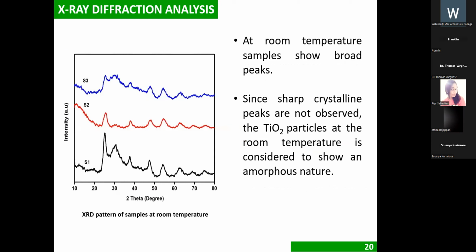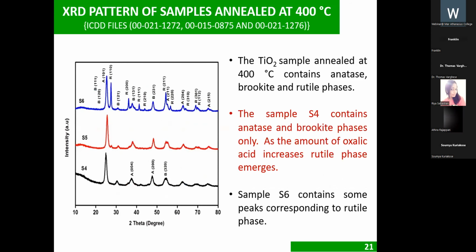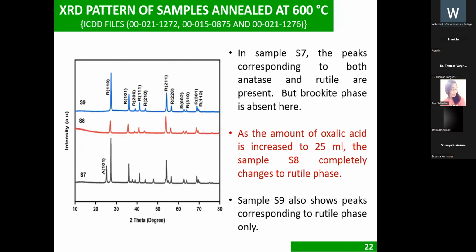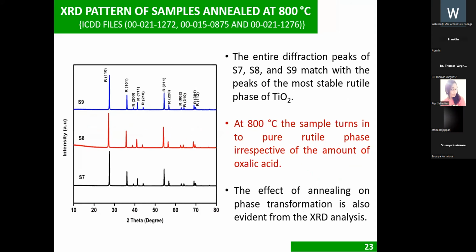here, S1, S2, S3 samples. Clear, sharp crystalline peaks are not visible, so I considered it as amorphous. And when it is annealed to 400 degrees Celsius, three different samples are here with 0, 25, and 50 ml oxalic acid. And as the amount of oxalic acid increases, the rutile phase of TiO2 begins to emerge. In the case of the 600 degrees Celsius samples, for the first sample, S7, there is a peak corresponding to anatase. But from S8 onwards, only the rutile phase of TiO2 is visible. In the case of the 800 degrees Celsius samples, irrespective of the amount of oxalic acid, all peaks correspond to the rutile phase of TiO2.